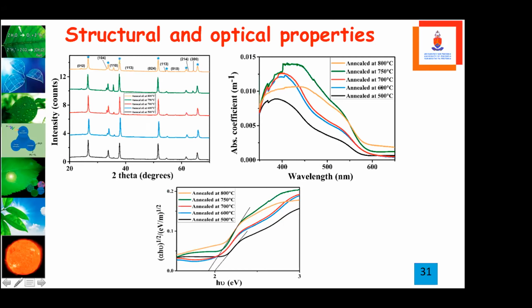When we did our annealing studies, we found that you can anneal hematite from 500 to 750, but if you go to 800, something else happens, which is an example of the dislocations becoming bad in this material when you anneal at a higher temperature, so that there are traps and defects that are trapping electrons during the